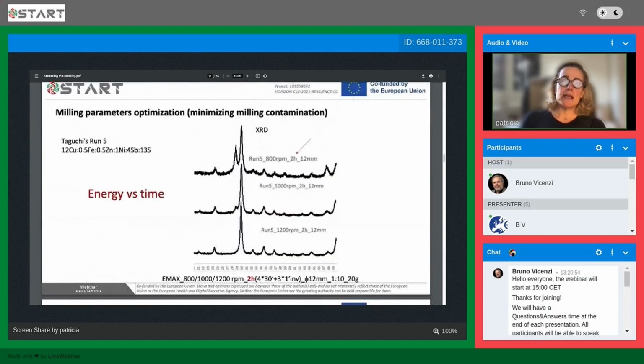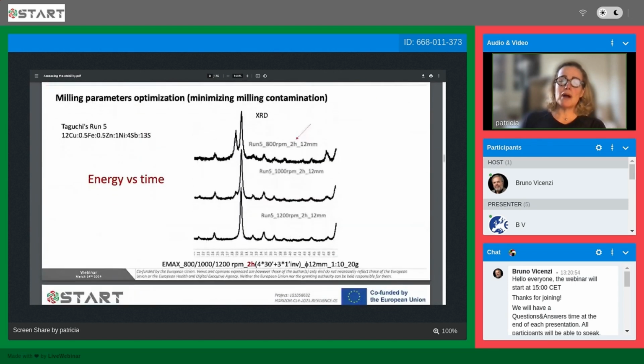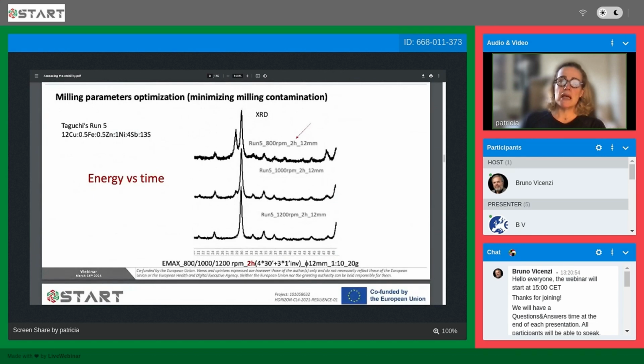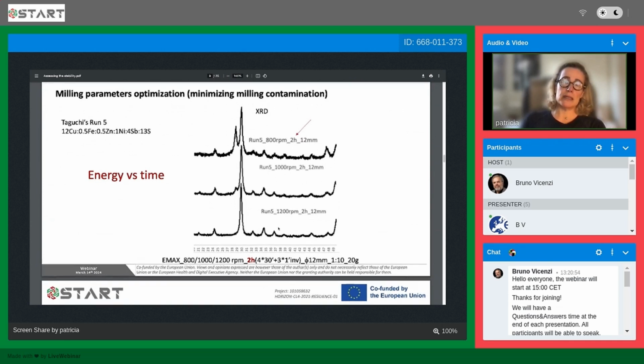And then we decided, okay, now let's go for 2 hours. And with 2 hours, we can see that for 1,200 rotation per minute, then we only have tetrahedrite. So we were able to select the parameters.